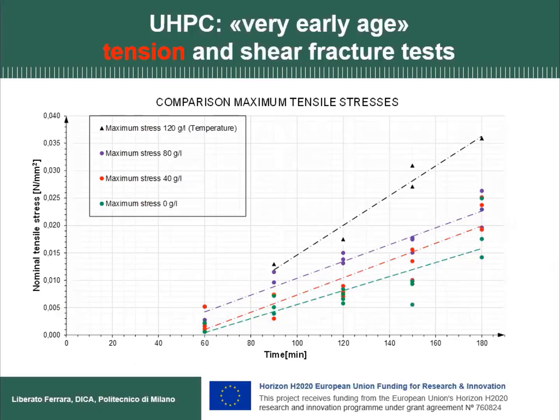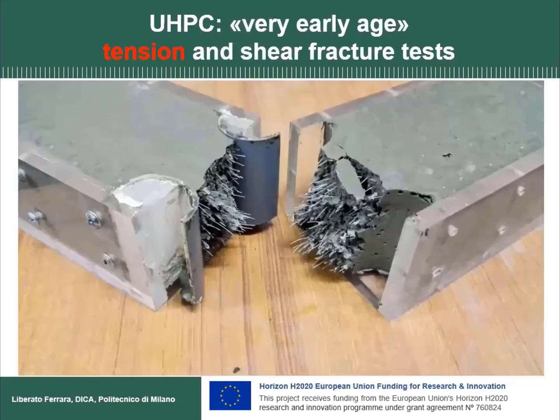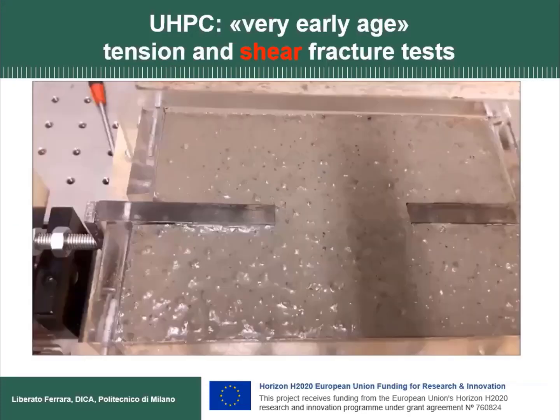We plot here the maximum tensile strength for the different dosages of fibers versus the time. So from 1 to 3 hours, you can see there is a clear increasing trend. And actually, you can see that there is some kind of change in the slope also at 120 kg of fibers per cubic meter. An image of the plot.